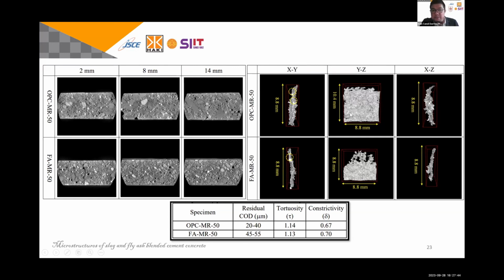And for flexural specimen, we also calculate, we do clustering, and then we have the crack in 3D, in 3 dimensions. As you can see here, the tortuosity is quite low compared to the splitting. So here we can summarize that the flexural crack results in lower tortuosity compared to the splitting specimen, and also the constrictivity is quite high compared to the splitting test.